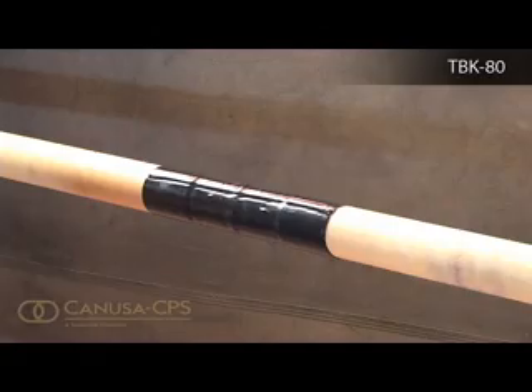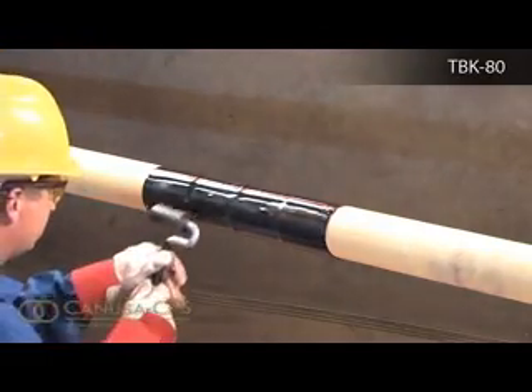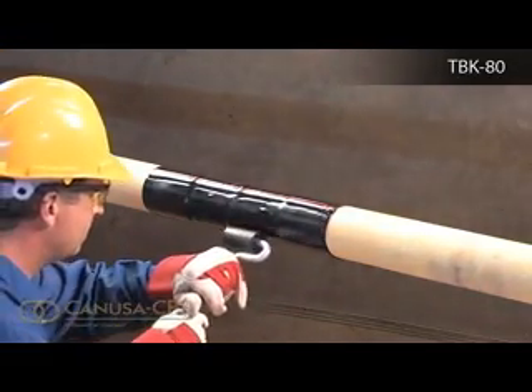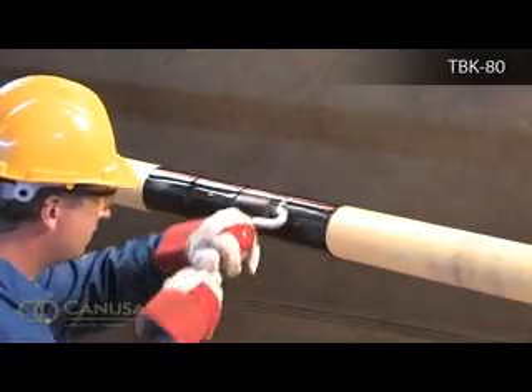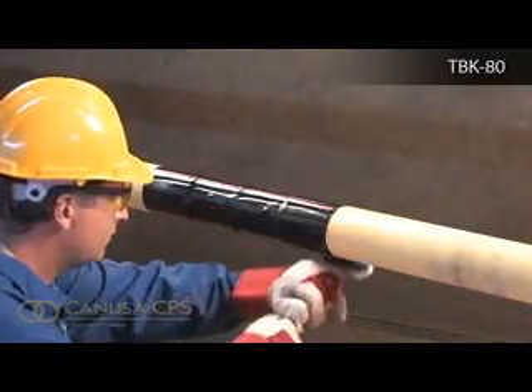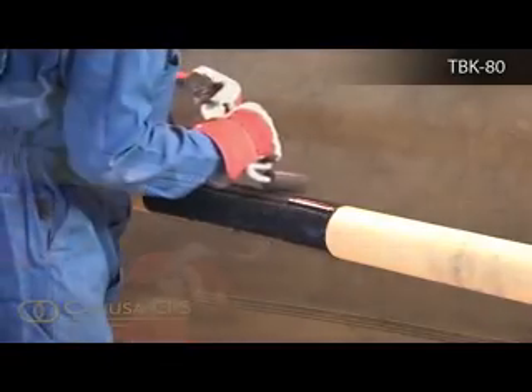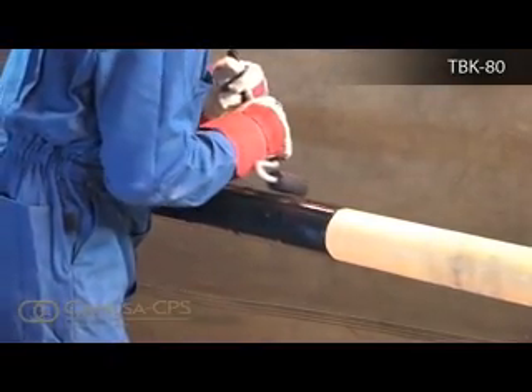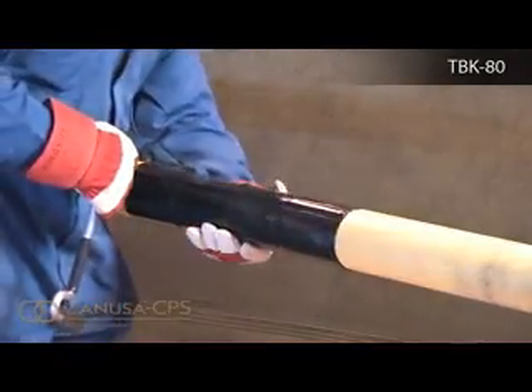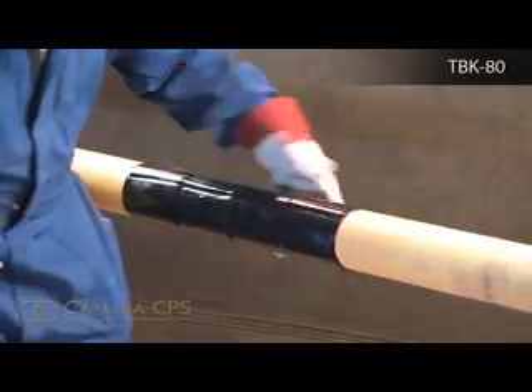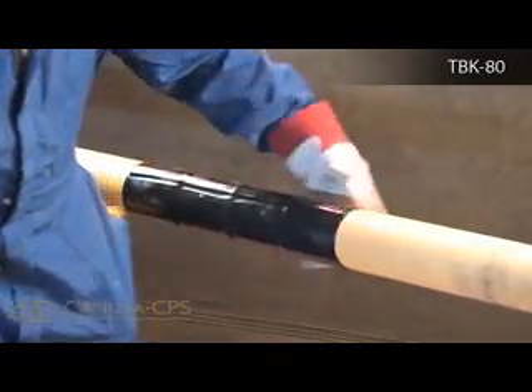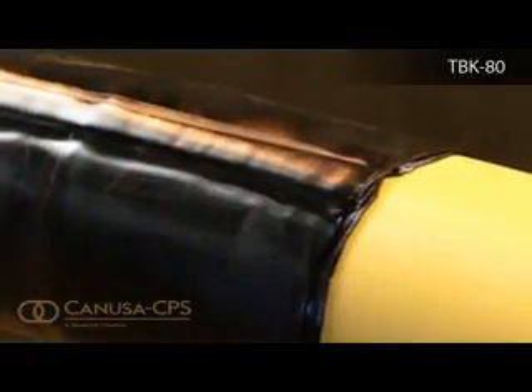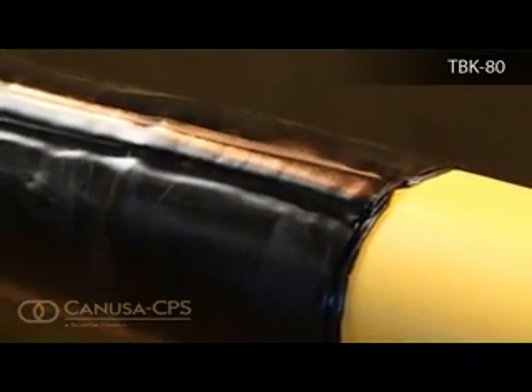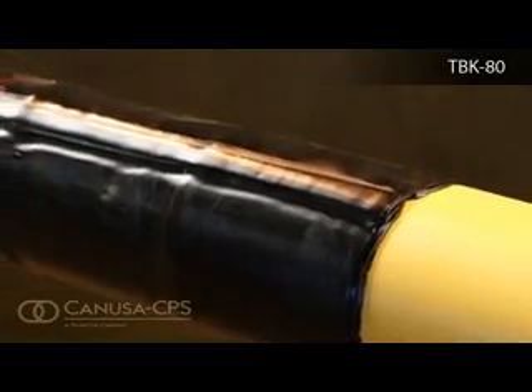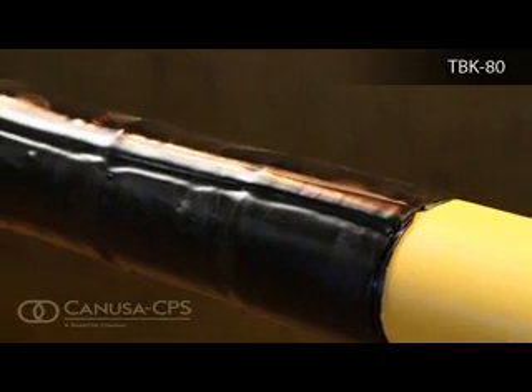While the sleeve is still hot and soft, use a hand roller to gently roll the sleeve surface and push any trapped air up and out of the sleeve. Continue the procedure by also firmly rolling the closure with long horizontal strokes from the weld outwards. Visually inspect the installed sleeve and make sure that the sleeve is in full contact with the steel joint, that the adhesive flowed beyond both sleeve edges, and that no cracks or holes are in the sleeve backing.